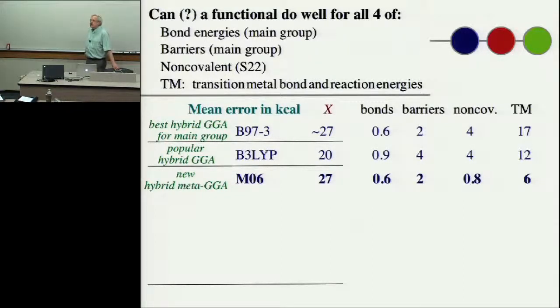We had some functionals that had only one parameter that did pretty well, and then we went to functionals that had 6 parameters and they did better. And we felt we were learning how to design the correct functional forms. And so we got large, diverse databases, and we started going to higher order polynomials in our functionals. And we found we could go to 20, 30, and 50 parameters, and we got stable results. We could predict results that were outside of our training set. So for the most part, we're willing to accept this larger number of parameters because we think it's just a convenient way to represent a complex function.